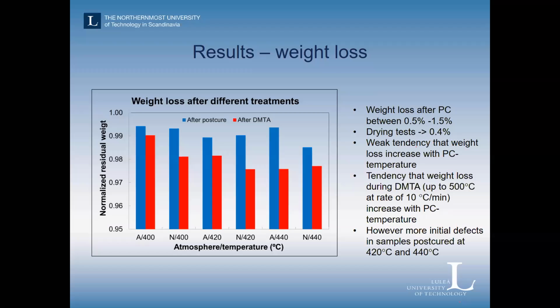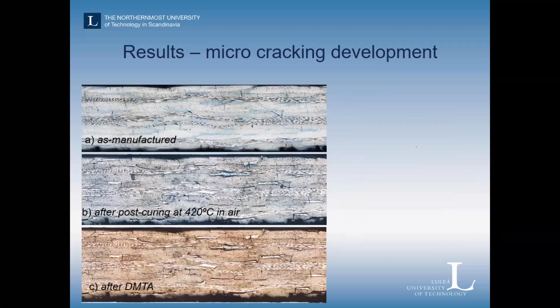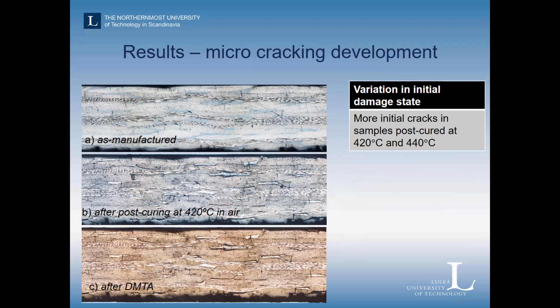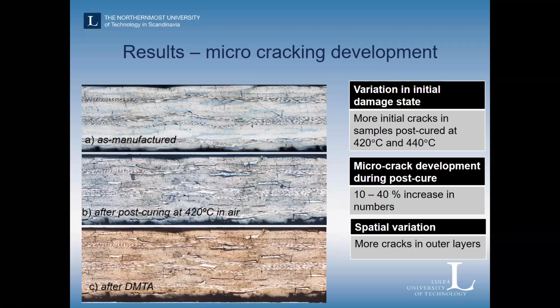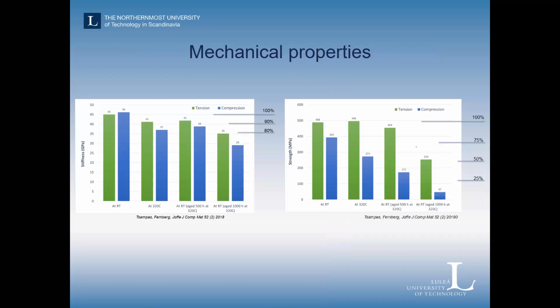It was a bit difficult to conclude much because of the variation in initial properties of the material. When we look at this material, we notice that there are micro cracks developing on the surfaces due to the aging, and the increase in numbers is around 10 to 40% on the edges. There are more cracks in the outer layers, which is clearly something that needs to be taken into account when looking into how they operate on the surface.